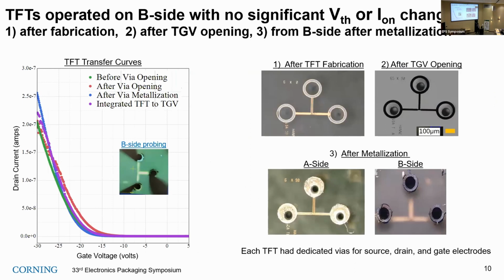These are some of the electrical results after we probed the TFTs from the backside. You can see the steps of each: after TFT fabrication, after TGVs are opened, then metallization from the A side and then B side, and then we probe. The biggest thing is we track the TFT performance at each step of this whole complex integration, and we see no or very minimal shift in the threshold voltage of the LTPS TFTs as they go from the front side to the via opening, then metallization of the via, and from the back side. So with that, I will go on to the next step.